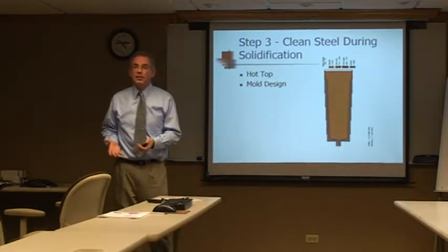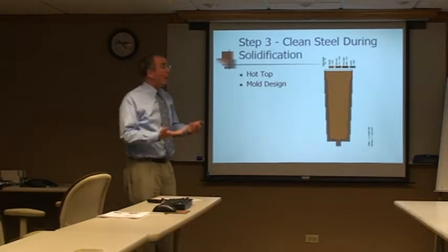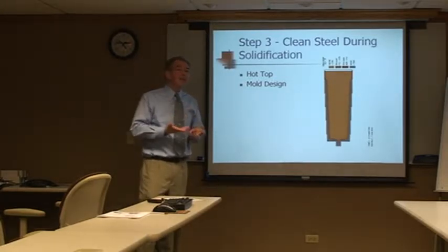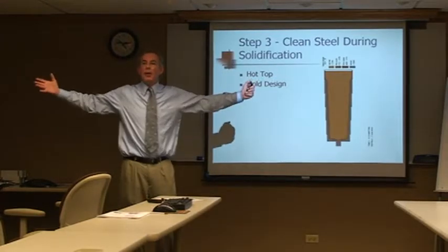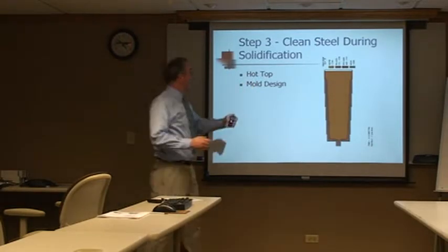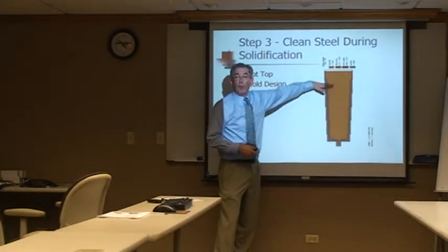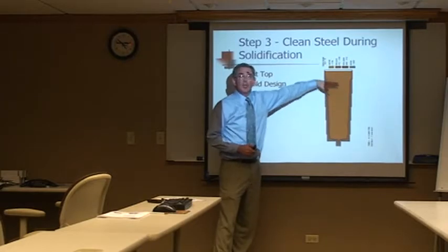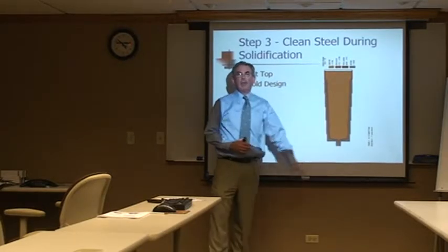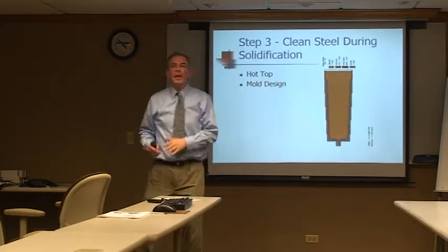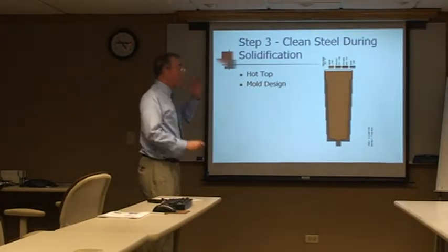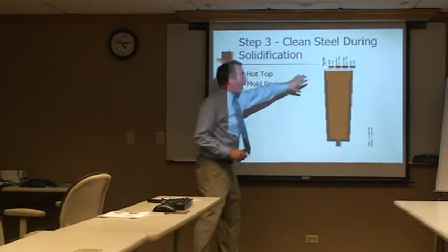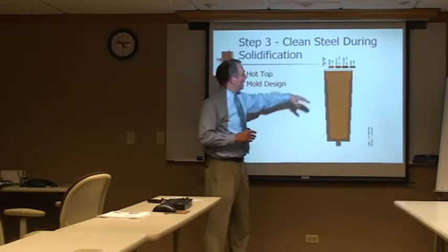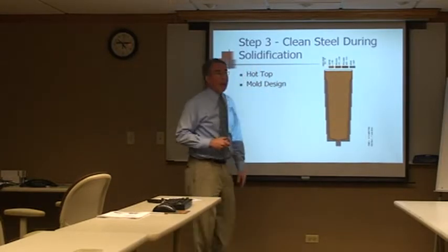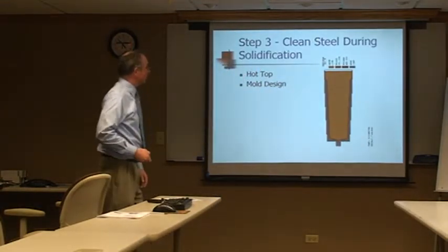So instead of losing 50%, by using a hot top we're able to lose 10, 15, worst case 20% on a very large ingot. But it's very defined, so when you guys forge, you see where the hot top junction is. If you crop at the junction, everything below that is going to be good. Because of the mold design, because of the hot top design, everything is figured and balanced to allow ideal solidification.